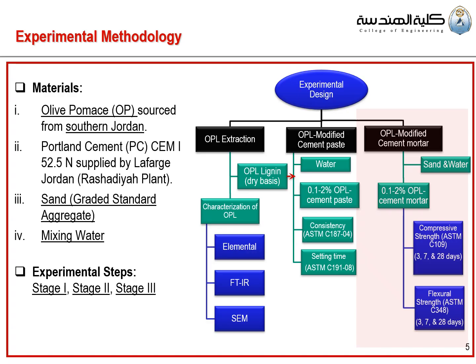Stage 3 is focused on strength testing. We want to see the performance of modified cement mortar, so we add the lignin with cement, sand, and water, using the same dosages from 0.1 to 2% by cement weight. We test the compressive strength by the ASTM specification. We develop values for all curing ages, 3, 7, and 28 days, and also for the flexural strength at 3, 7, and 28 days.